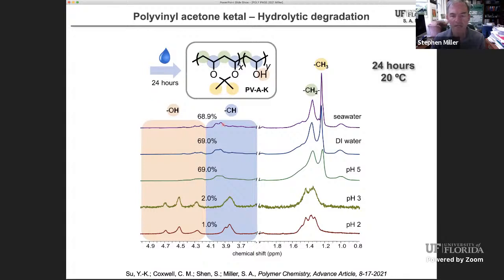So what about their degradation? If we throw this polyvinyl acetone ketal in low pH aqueous media, such as pH 2 or pH 3, we see a pretty rapid hydrolysis, almost complete hydrolysis in the time span of 24 hours. But at pH 5, with deionized water or seawater, we essentially see no hydrolysis after a day.